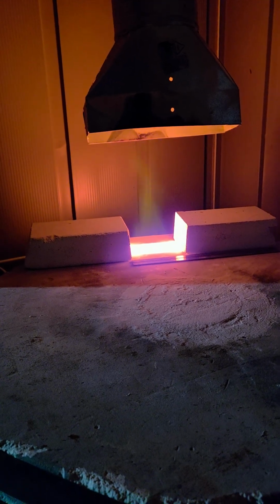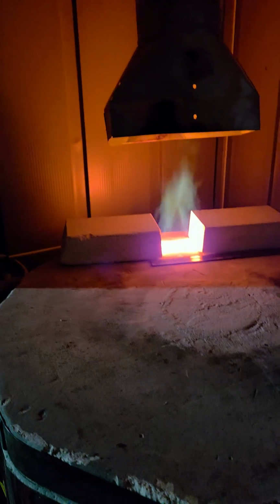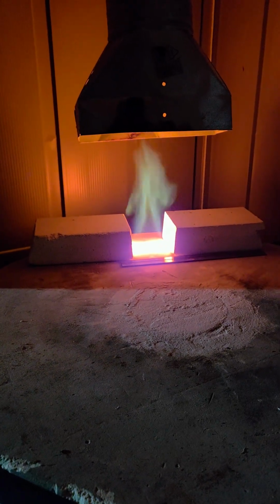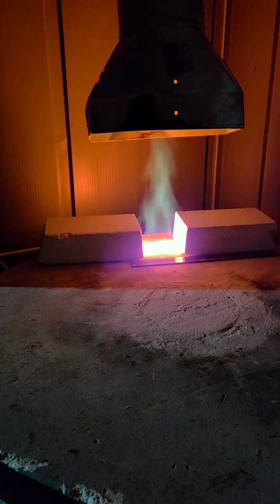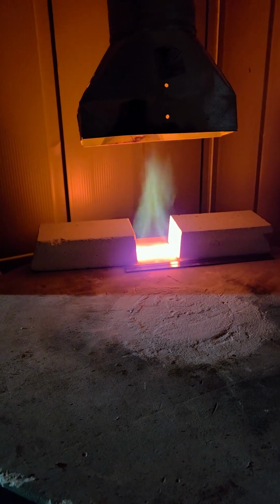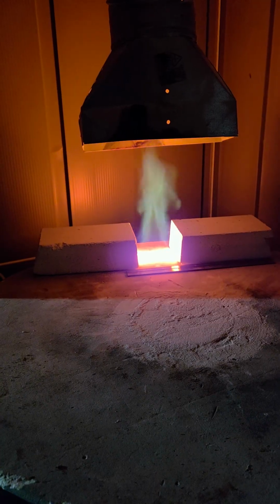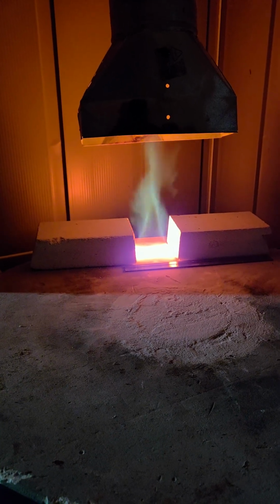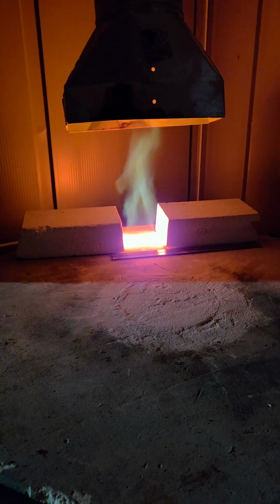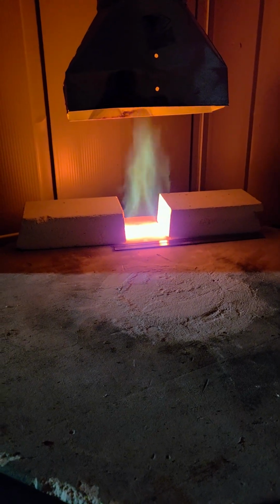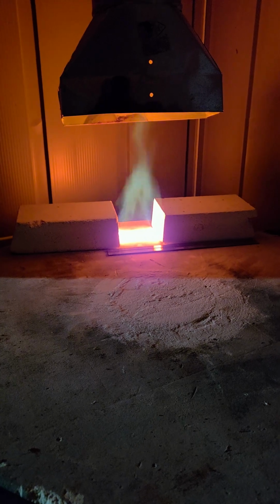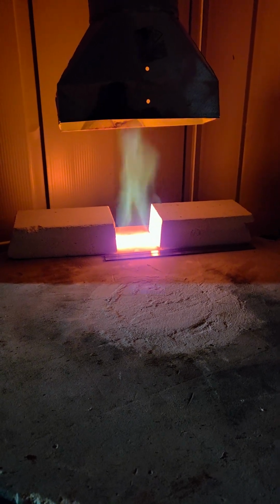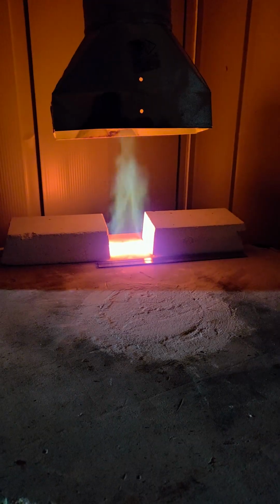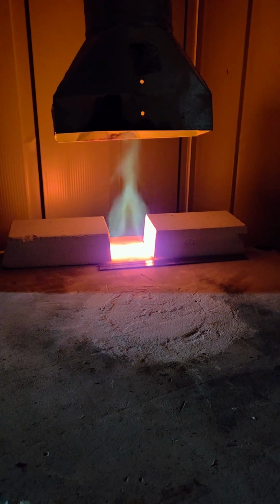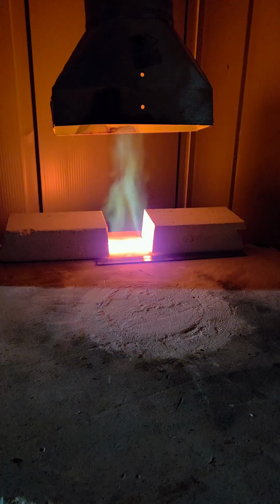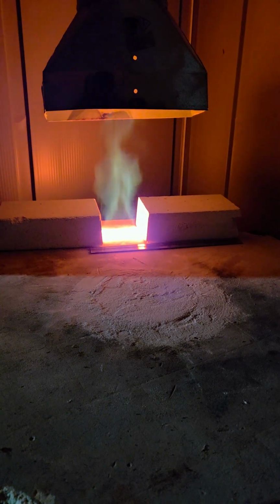Well, it's about 12:35, and cone 10 has just gone down, and I've choked off the kiln a little bit to 3.5, maybe 3 3/8 inches, and I've lowered the pressure to 1.6 psi. It's causing the temperature to drop slightly, but this is kind of an evening out procedure done at the end, and it just helps to stabilize the temperature. It's very similar to what's done in an updraft kiln.